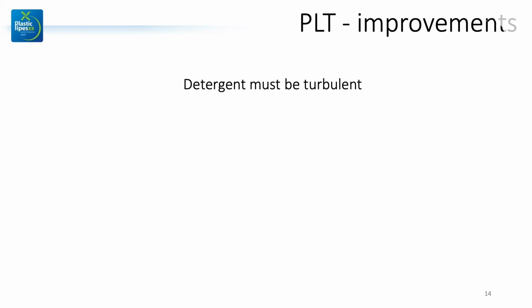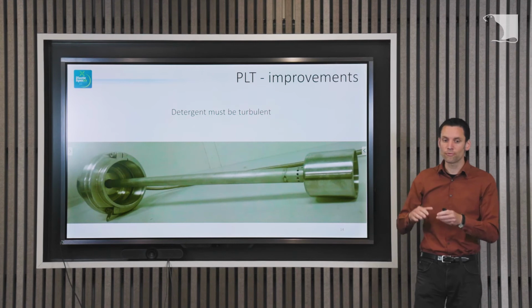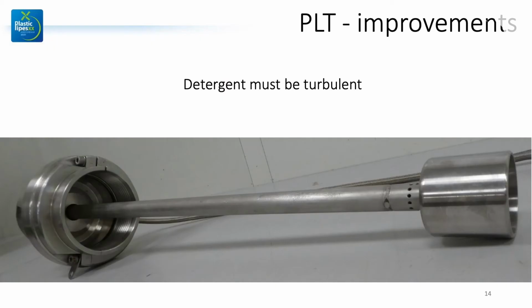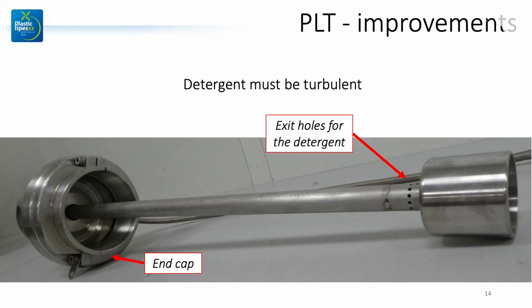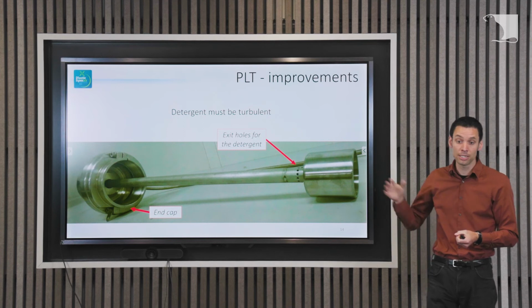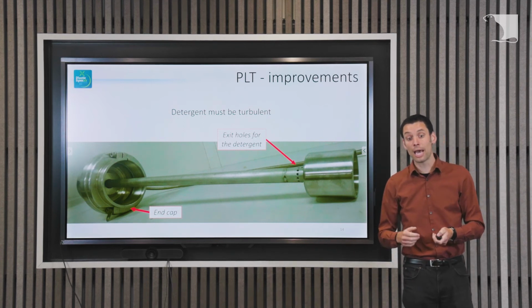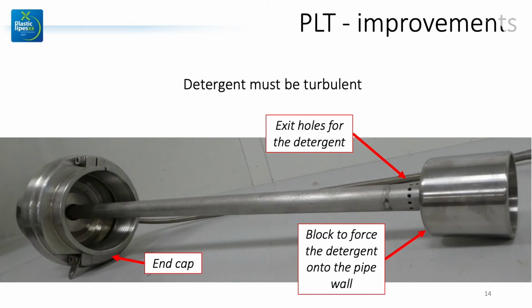The second point is, how is the flow of the detergent inside the pipe? It must be turbulent. It must get to that inner surface where the point load is pressing on. So what we did, we made a sort of internal spray system, which is already used by one of the two other labs. So here you see it. It is an end cap. Then you have a sort of rigid hose, which has some exit holes on the outer end for the detergent. And we have a block, so really the detergent is forced exactly at the spot where the point load is. So this is what we did, still under development.